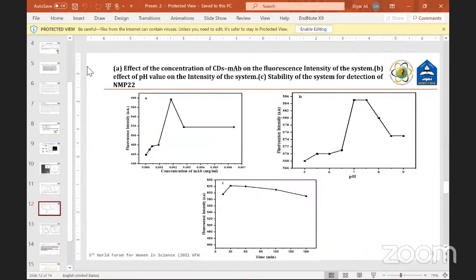Then we did the study of the effect of concentration of carbon dot conjugated to MAB, monoclonal antibody, on the fluorescence intensity, and the effect of pH value on the fluorescence intensity. Then we studied the stability. As is clear, we get the maximum at this concentration for the antibody, and the best pH for working is pH 7, and the reaction starts to be stable after nearly 13 minutes. After that, the reaction remains stable.